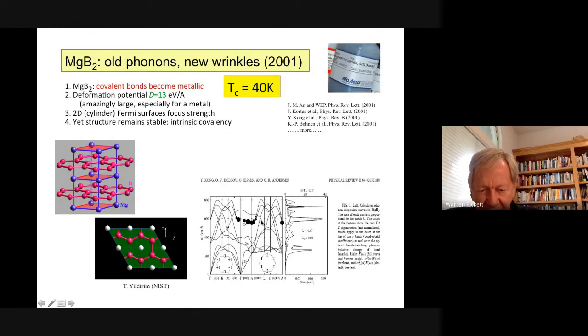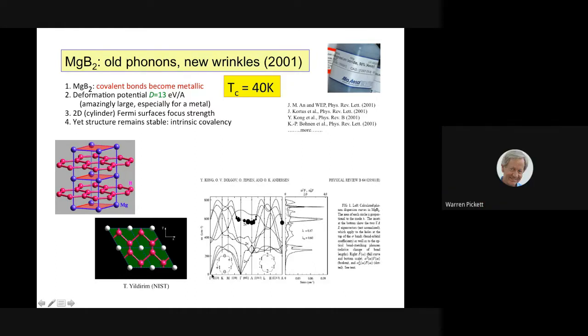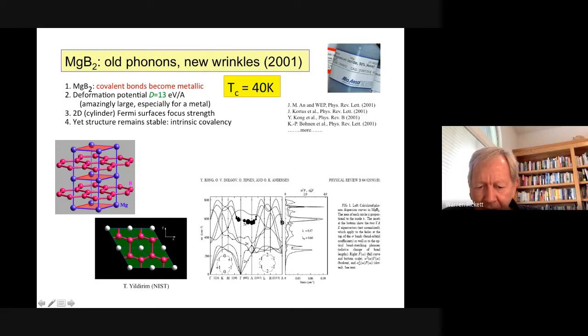I won't go into this much, but this is a plot of the phonon frequencies, the lattice vibrational frequencies, versus different directions and magnitudes of the momentum. You get these branches like this, and the dots shown here show the strength of coupling of that particular phonon to the electrons at the Fermi surface. What you can see here is most of the places you can't see the dots. The area is proportional to the strength of coupling, but there's this top optic branch, which is this mode. There are two of them because it's two-dimensional. Those are extremely strongly coupled, and that's why this is a 40 Kelvin superconductor.